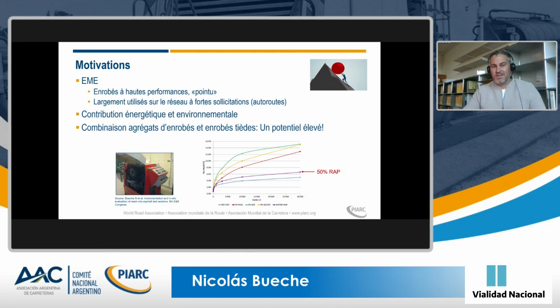Motivation is quite easy, let's say. For the National Road Administration, we work using high modulus asphalt. So you have a top layer, then we have 2 layers of high modulus asphalt, which, at the national level, we use quite a lot. And now, as everybody, we have this sustainability issue, and we believe that we have to bring a substantial contribution to the energy and environmental aspects. And that's why the National Road Administration said, okay, we want to produce this high modulus asphalt in a warm mix perspective, but adding a high percentage of reclaimed asphalt, which is a bit tricky. So we have high modulus plus warm mix plus a high RAP content.